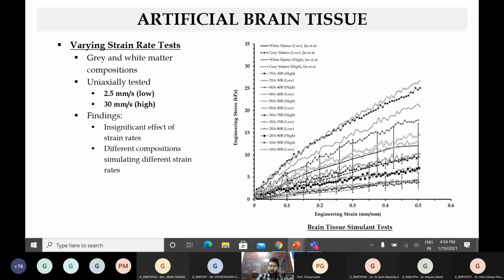We are again trying to plot. So the first 4 plots here with the error bars, you're looking at the white matter and gray matter properties at the high and low strain rates. The low strain rate is 2.5 millimeters per second and the other one is 30 millimeters per second. So these are the actual tissue properties, and 70A 30B, 70A 30B, low, high, these are all different compositions which are tested at different strain rates.